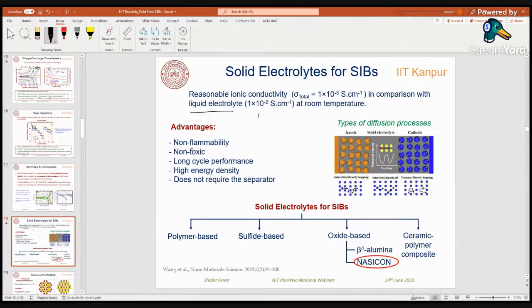These solid electrolytes are non-flammable, they are non-toxic, they can go for longer cyclic performance because there won't be any dendrite growth inside the material, and also they can give you higher energy density. How? Because they have a potential window which is larger. So you can basically use higher voltage cathodes with this type of solid electrolyte. And of course, since they provide a physical barrier, you do not require the separator in the battery cell.